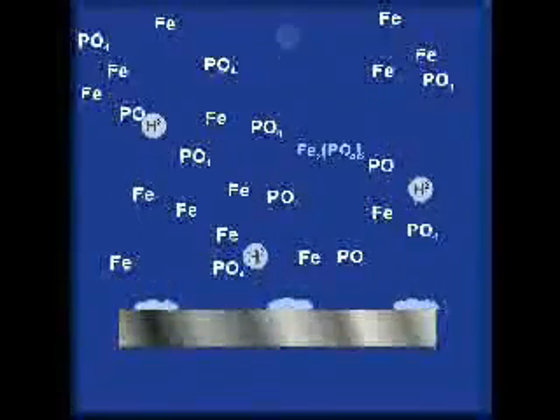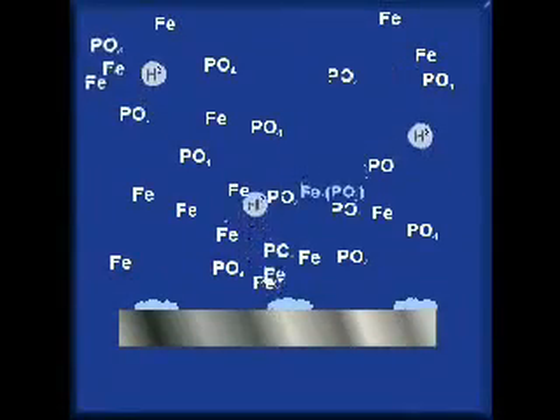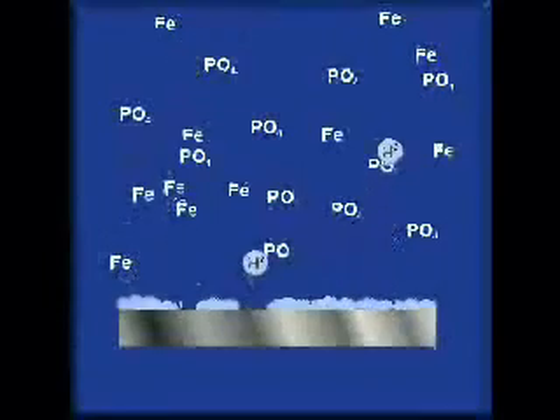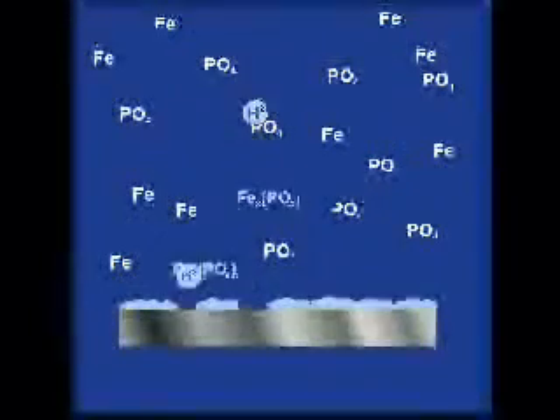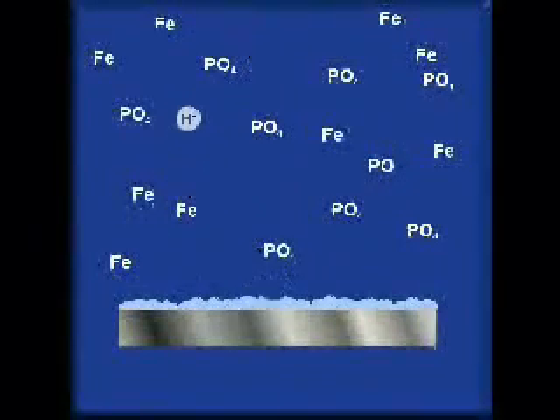As pH increases, the dissolved iron will combine with the phosphate in solution and precipitate and redeposit on the part. pH control is critical. At pH below 3.5, the part will pickle, but precipitation will not occur. At pH above 6, the part will not pickle. As the iron phosphate layer builds on the part, less iron is available for dissolution. Thus, the iron phosphate coating is self-limiting.